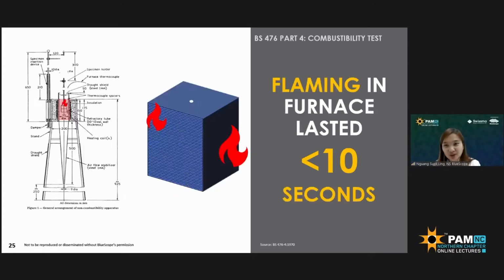Another criterion is that there shouldn't be any visible flame within the furnace area that lasts more than 10 seconds. So if any visible flame is observed and lasts for 10 seconds, then it failed the criteria.